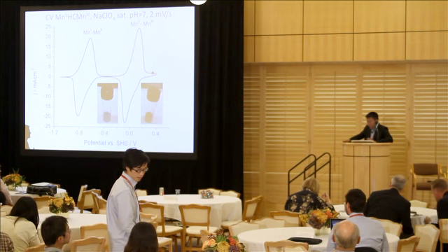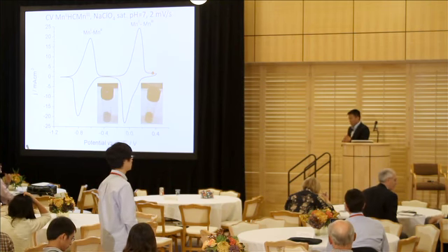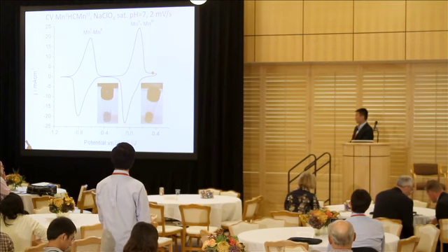Any other questions? Well, I have one last question for you. So you showed the 60 milliamp hours per gram. I was curious how close that is to the theoretical maximum for this type of material. For these materials, the theoretical maximum is somewhere around 60 to 70. So it's already close to that.